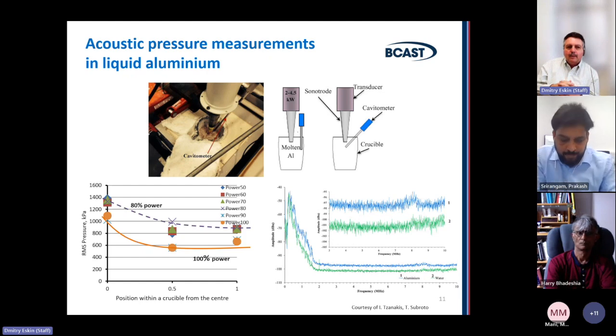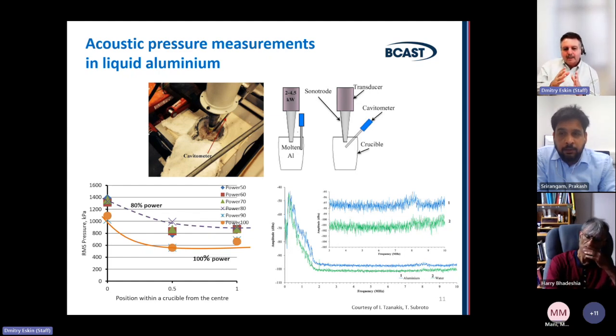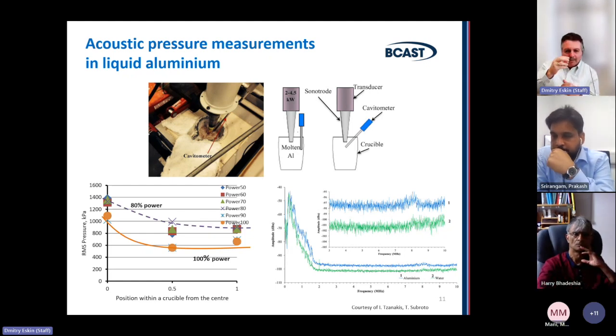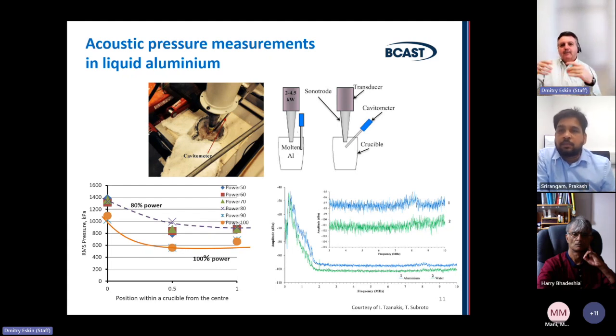And if we talk about degassing of aluminium, this is practically realized in the selection of temperature. When we want to degas liquid aluminium, we usually select a range between 700 and 740 degrees, where the viscosity is still quite good, because the closer you go to the liquidus, the viscosity of the melt increases and density increases. So the bubbles have more difficulty to float. So you need to have a good temperature range where these bubbles can be created and rapidly released.